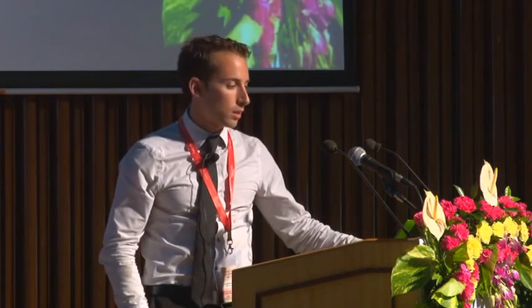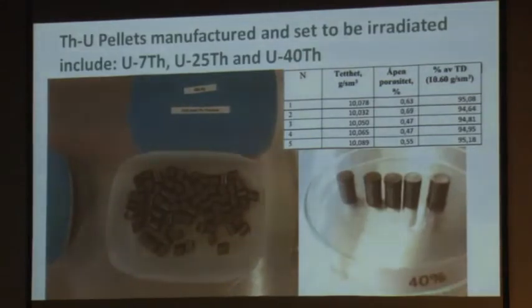We've also been manufacturing thorium-uranium fuels. We have three variants, those containing 7% thorium, 25% thorium, and 40% thorium. The picture on the left there is our 7% material, whereas the picture on the right is the 40%. And we assumed that the 40% was going to be the product that was going to be harder to attain, which it ended up being. But we were able to ultimately fabricate pellets with about an average of 95% of theoretical density. Here's a picture of me and two of my colleagues in the uranium lab holding up some of the first thorium dioxide additive pellets that we created. This picture is about 3 years old now.